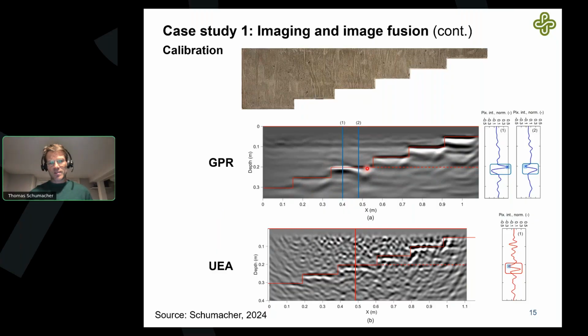The reason is we put a piece of steel against this step here, and the rest are basically just against air. So if I take a vertical cross-section through this part and one through this part, you can see that the received pulse is opposite. What that means is I can look at the reflector in the image and tell something about the type of reflector I have. I can tell you whether it's air or metal, or we could also tell whether it's air or water.